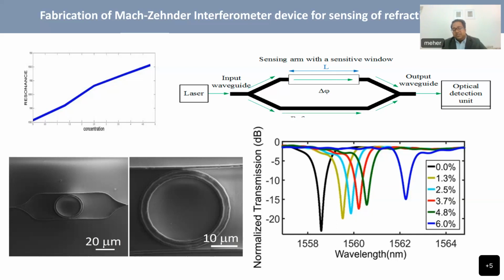We tried measuring the refractive index here, and we could see that at different concentrations we have a peak shift in the results. This concentration is because we used sodium chloride solution. Sodium chloride solution is a very conventional solution for getting very precise refractive index. Different concentrations have different refractive index, and the range is good. So we can see that the peak shift is happening here. But these kinds of sensors cannot be integrated easily on integrated circuits.